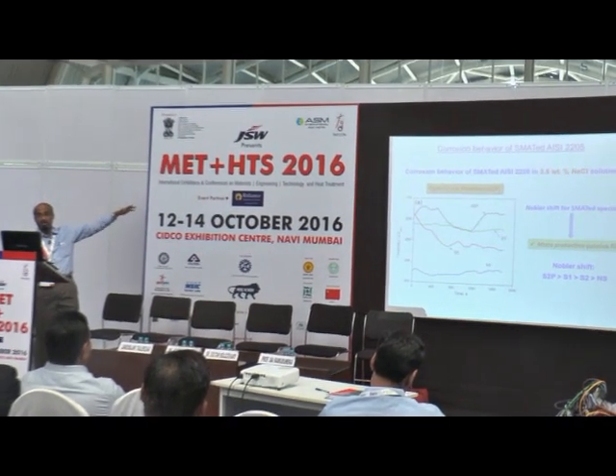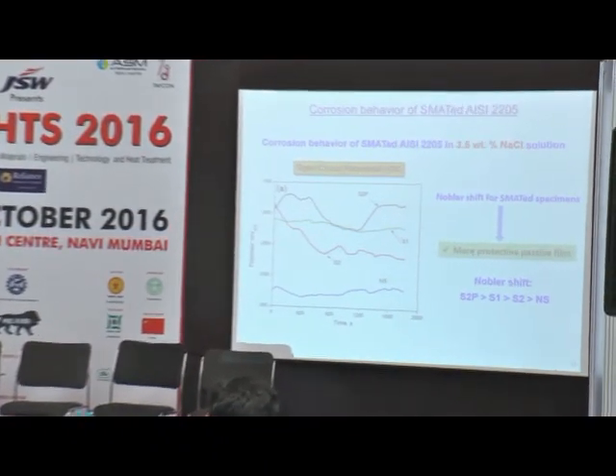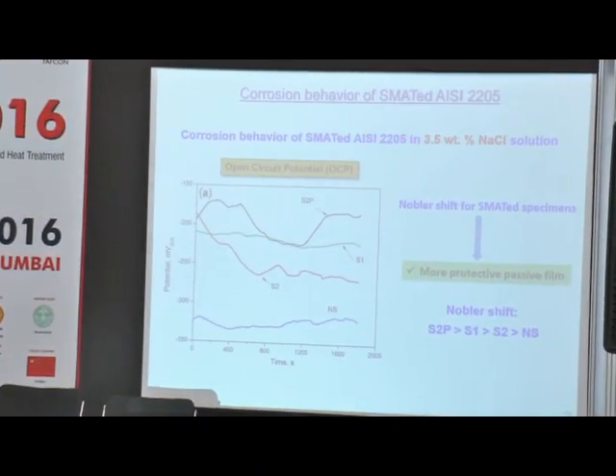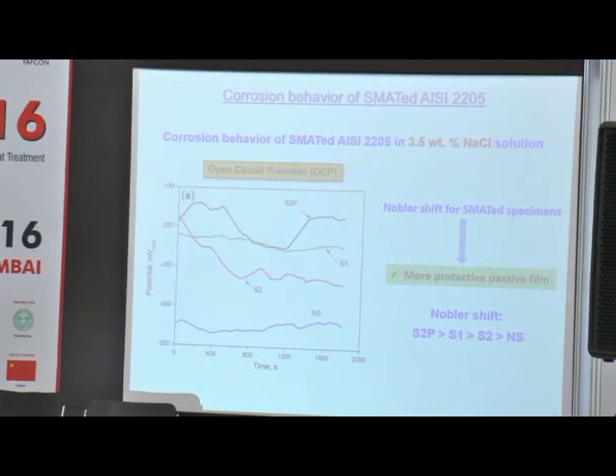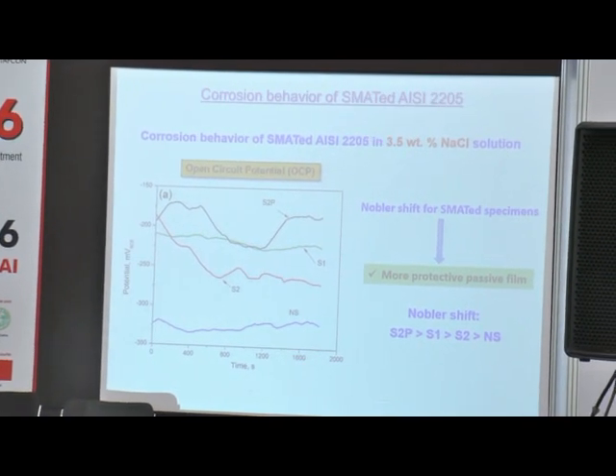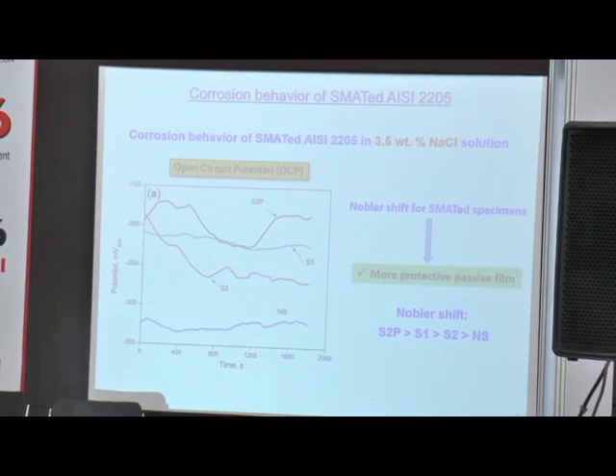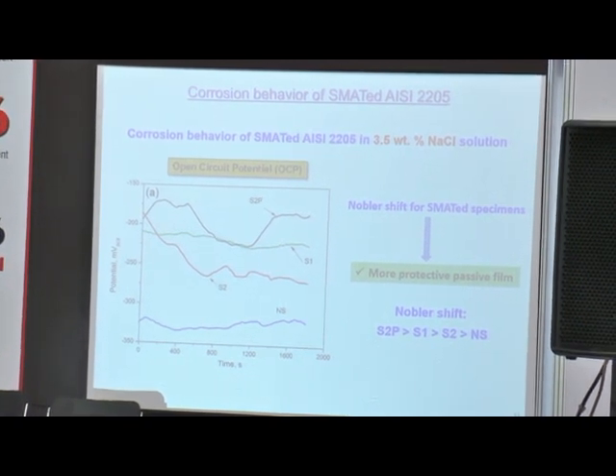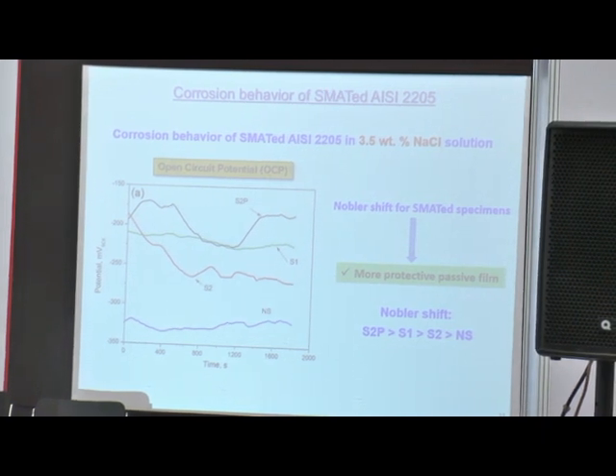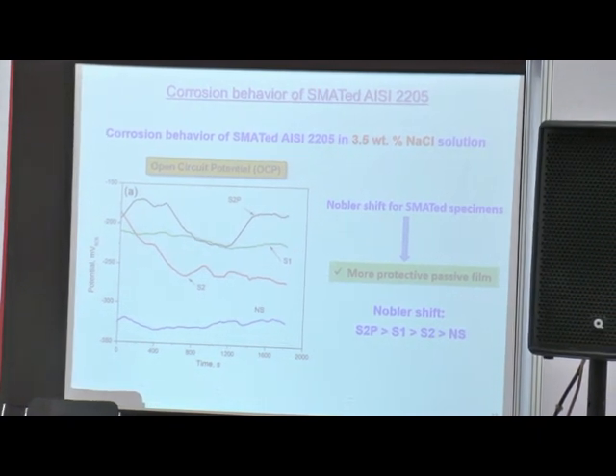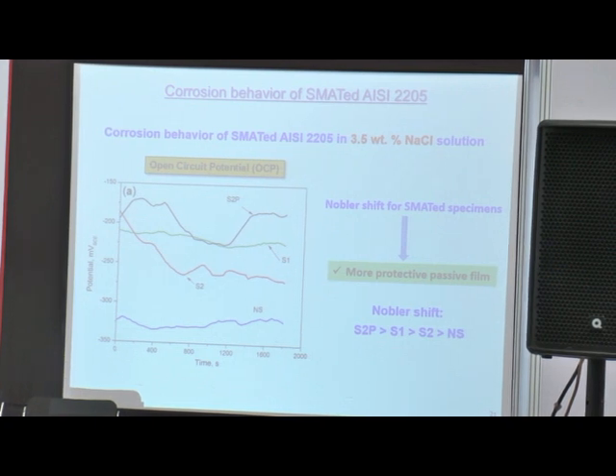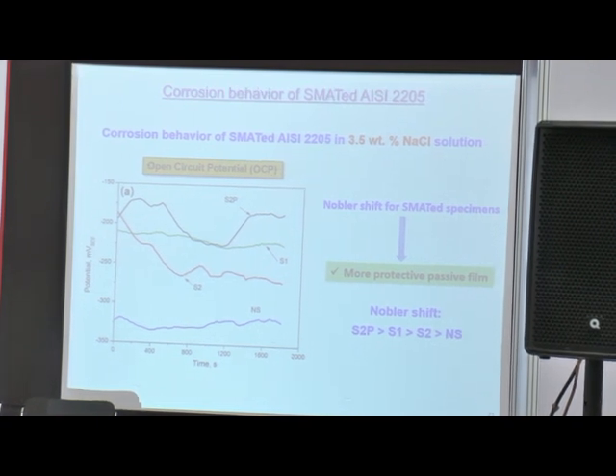What we observed here is that the bottom line is for the non-SMATed specimen. As you do the SMATing, the open circuit potential value increased, it is shifted upward. That means your corrosion behavior, your corrosion property, is now improved. In the SMAT process, the surface becomes rough, with roughness of about 0.5 micron to 1 micron. If you remove that surface roughness and observe the open circuit potential, it says that your corrosion property is further enhanced. That is the S2P, where P indicates the polished sample. So the polished sample has a better corrosion property.